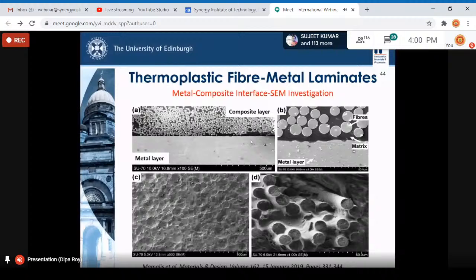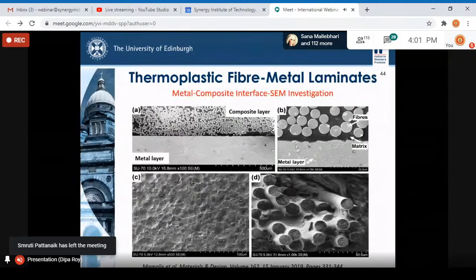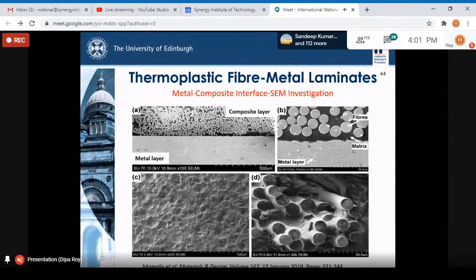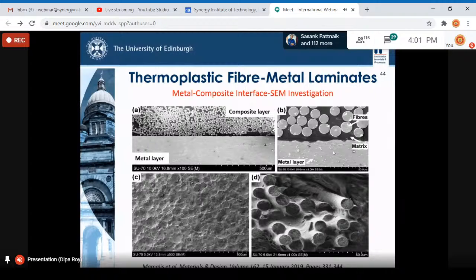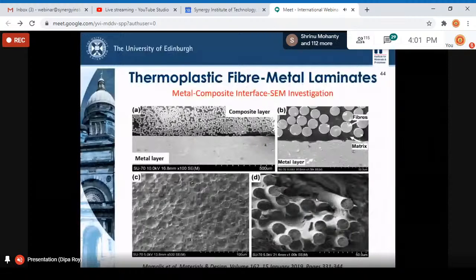Okay, so these were some images of the interface of the composite and the metal from our first set of laminates. Here you can see this shows quite good bonding. The lower layer is the metal layer, this is the composite layer, and this is the interface. It looks really good, with no interfacial gaps or anything present. The very low viscosity of the acrylic resin is highly beneficial in wetting the metal surface. It can flow very well, and since the surface preparation also facilitated it, we got quite a good interface even in the very first set of our studies. And this is in the composite layer. The fiber matrix bonding in the composite layer was very good as well. So overall, this was a very positive start to this research.